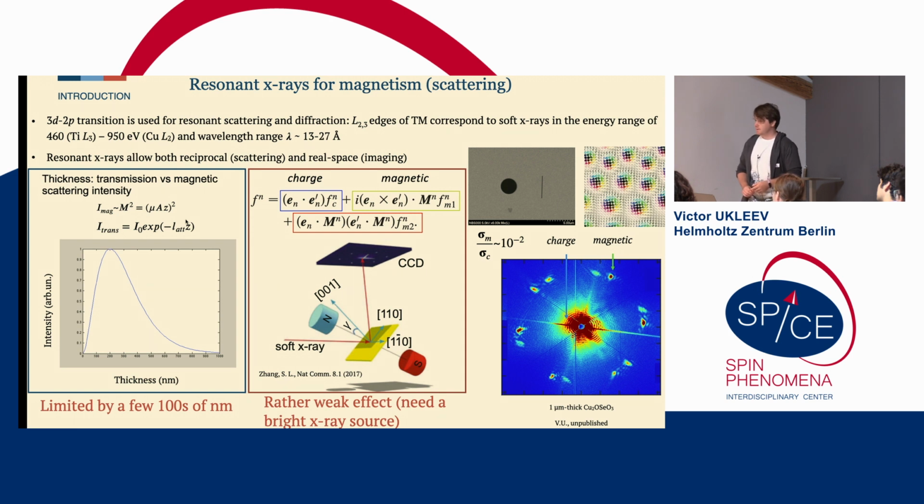But if you have a spatial separation in the reciprocal space of your magnetic modulation vector and your charge modulation vector, like if you have an antiferromagnetic material or a helimagnetic material that gives you incommensurate magnetic satellites, like the ones you can observe in the copper oxyselenide, as was discussed yesterday, you can rather easily separate charge and magnetic scattering and investigate your magnetic structure directly.